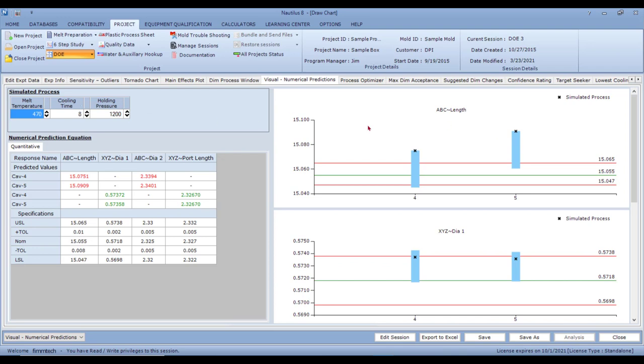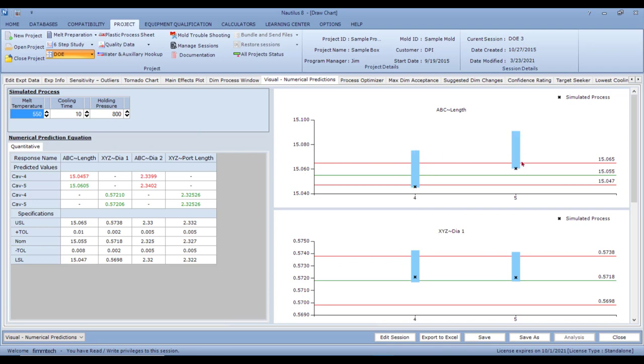The maximum dimension change for this length is shown at the top of the window. The blue column represents the range of dimensional change possible based on the molding process. I cannot make a dimension change above or below this column — if you look at diameter 2, the blue column is completely outside both the lower and upper spec limits, clearly telling you that no matter what you do at the molding machine, you will never bring this in spec through process changes alone.